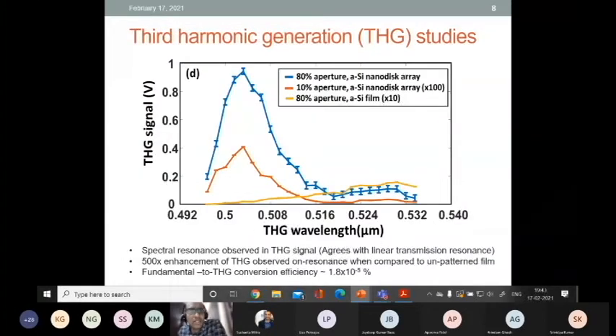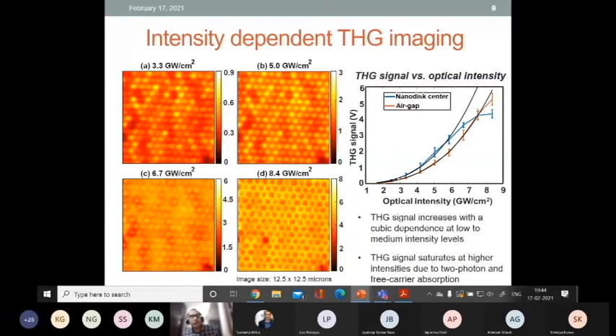With these kinds of structures, we have been able to look at harmonic generation enhancement. What you see here is a third harmonic generation enhancement study, which we did on these silicon nanostructures. We have achieved an efficiency enhancement of about 500 times. The conversion efficiencies are still on the lower side, so there is a need for new, more efficient nonlinear media, which can increase these efficiencies further, improve the quality factor, and help excite some of these resonances more efficiently. And our microscopy system also allows us to do spatial mapping of some of these samples.